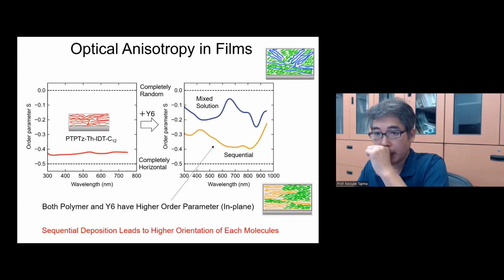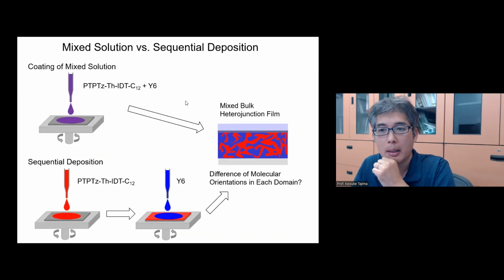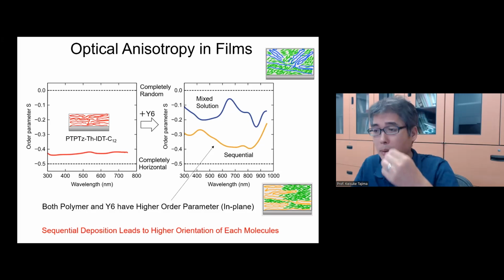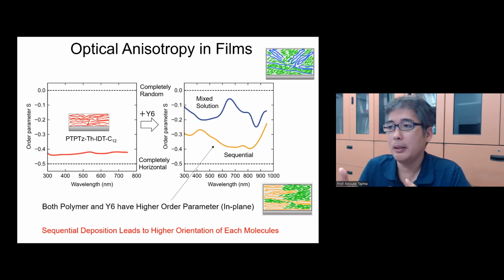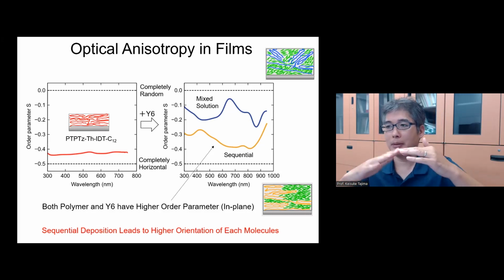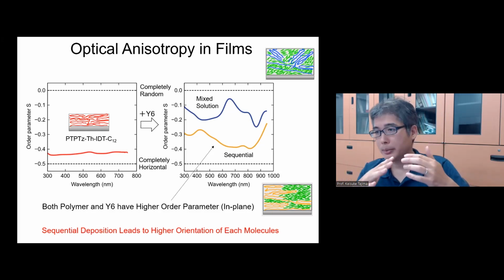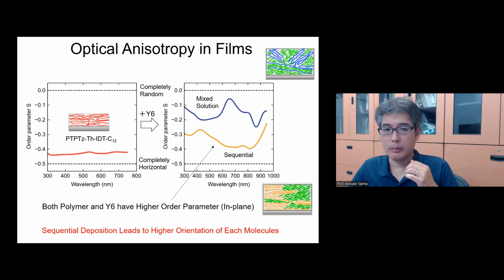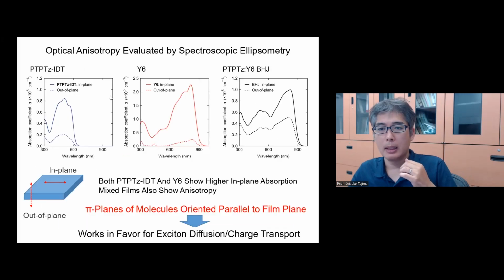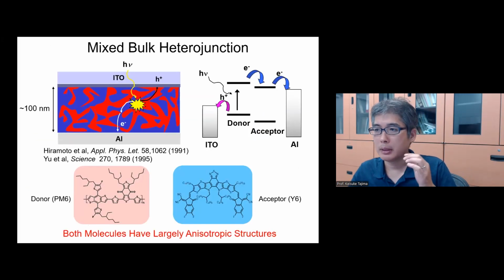Annealing process. I don't know which part they want to know, but in general, polymer, even annealing at high temperature, doesn't melt, right? So it's above the Tg, where local motion starts to happen. So orientation can be affected, but I would say not drastically. For example, in the face-on orientation polymer case, we annealed and observed some improvement in the orientation, but it's not much.